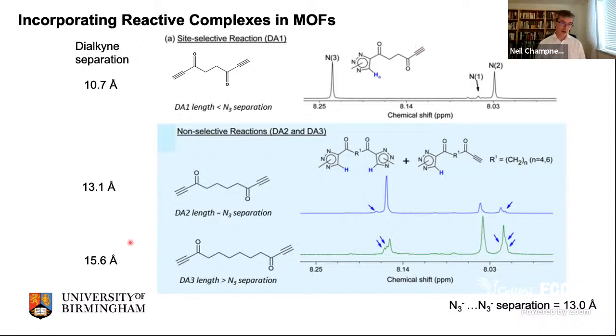If you take a dialkyne which is significantly longer than the azide separation, then you actually make the ditriazole compounds like this, and we still have a trace of this because we get an incomplete reaction. And if you have something which is almost exactly the right length, then you end up with a bit of a mixture of the different things. So this actually gives you some specificity in controlling that reaction process within the framework.